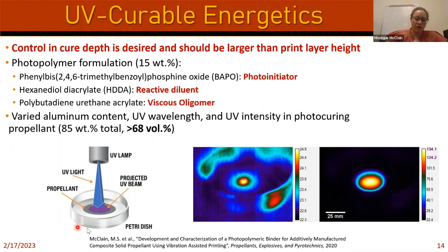We had some uncured photopolymer mixture or propellant mixture in our Petri dish. We had a light whose power we measured, applied over some area, and that's how we calculate our intensity. We apply that on the surface of this uncured mixture for a certain amount of time, then we turn off the light, remove the uncured portion, and measure the thickness after we cleaned it off.